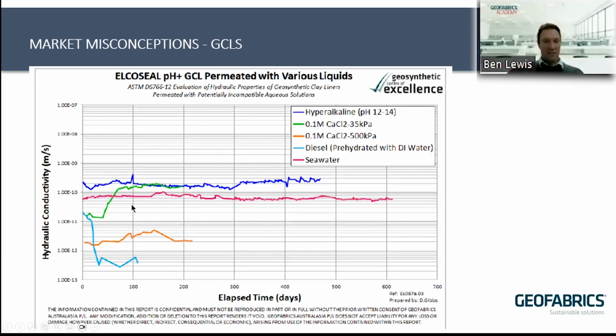We've done a range of testing with our GCL in hyperalkaline solutions, diesel, seawater, calcium chloride solutions, and you can see here none of these have dropped below that 1 times 10 to the -9 performance. Yes, they all vary in terms of how permeable they are, but you can see they still perform quite well. The worst performing solution was the hyperalkaline, but still well and truly above that, relatively impermeable product.